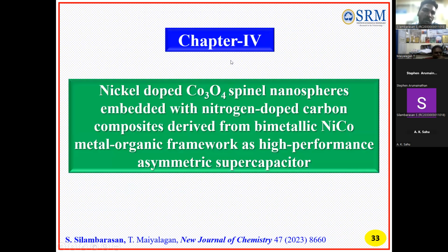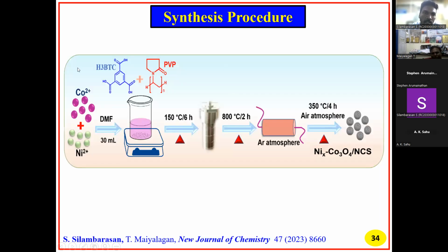Next, chapter 4: the nickel doped cobalt oxide spinel nanosphere embedded with nitrogen doped carbon composite, derived from the bimetallic nickel cobalt metal organic framework, as high performance asymmetric supercapacitors. In the synthesis procedure, the nickel doping was changed to three variations: 0.1 mole, 0.3 mole, and 0.8 mole. Then DMF was used as the solvent, 30 ml, and trimesic acid and PVP were added together and stirred for 1 hour.